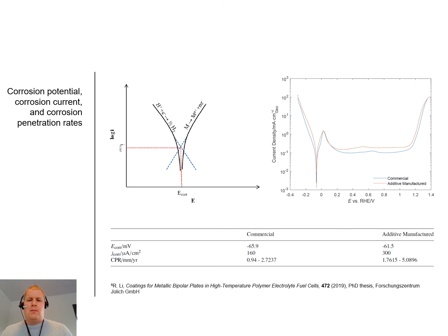In addition to being able to obtain the corrosion potential from this dip, you can also obtain the corrosion current density. As illustrated from this image here, you draw 2 straight lines in this manner, and where they cross, you can read off your corrosion current density. For our commercial sample, the corrosion potential was measured to be minus 65.9 millivolts, while for the additive manufactured it was minus 61.5 millivolts. Since both samples are Inconel 625, we are not surprised that they are relatively close to each other. For the corrosion current density, the commercial had a value of 160 microamps per square centimeter, while the additive manufactured had a value of almost twice as much, 300 microamps per square centimeter.